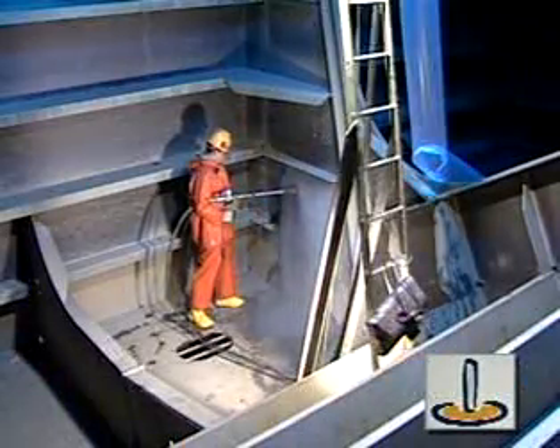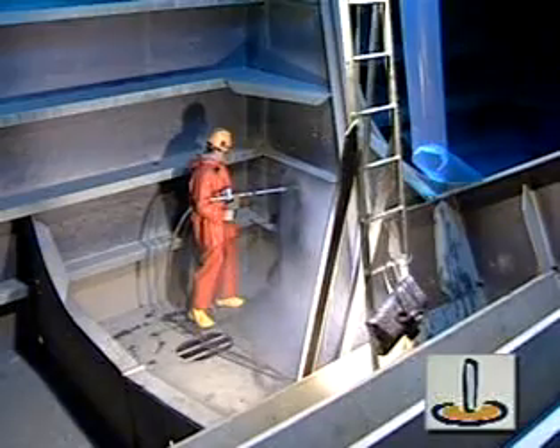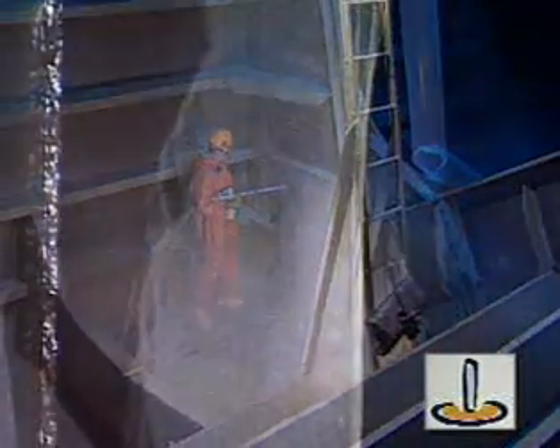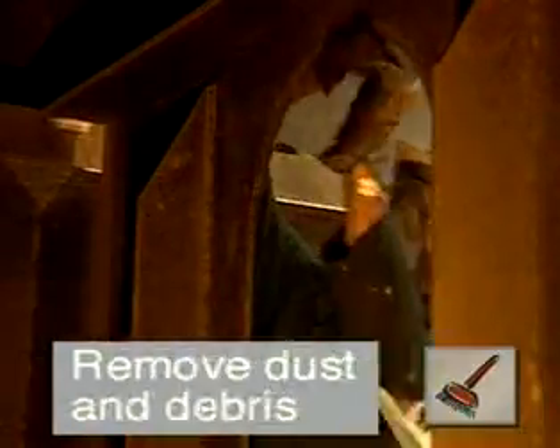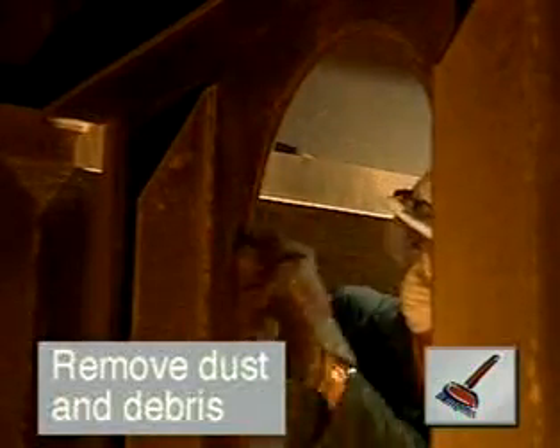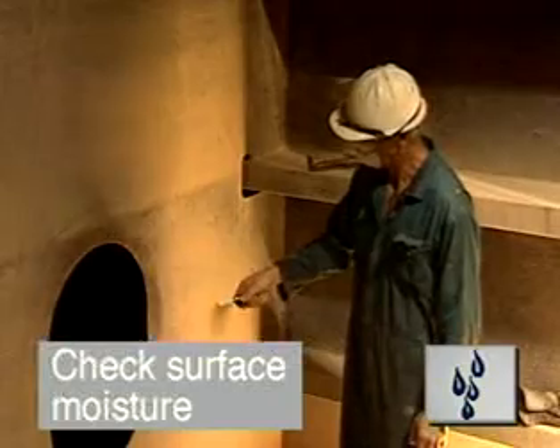Prepare the surface to remove all existing corrosion and feather surrounding intact coating. Hydroblasting is particularly effective in removing corrosion, minimizing salt contamination and feathering surrounding intact coatings in water ballast tanks. One drawback of the technique tends to be the rapid buildup of water mist on triggering the hydroblasting lance, which may slow the progress of surface preparation. Remove all dust and debris, or allow all water residues to drain and dry if hydroblasting has been used to prepare the surface. Check for surface moisture.